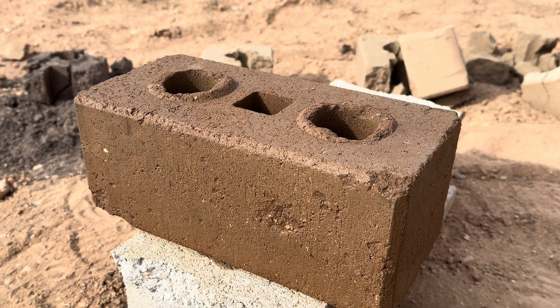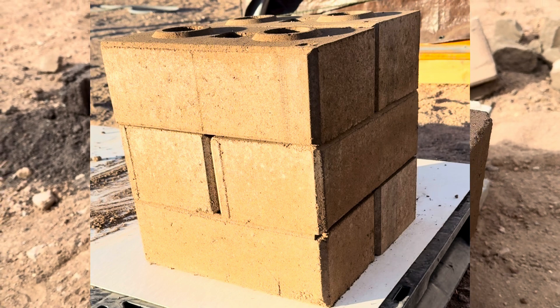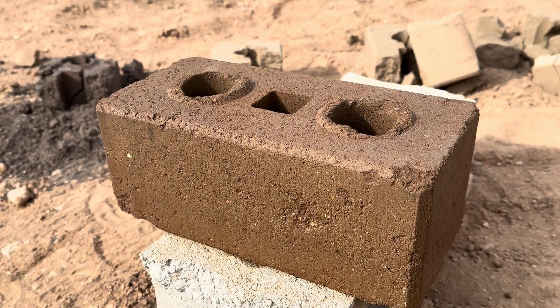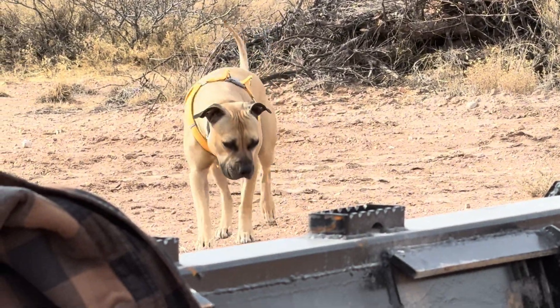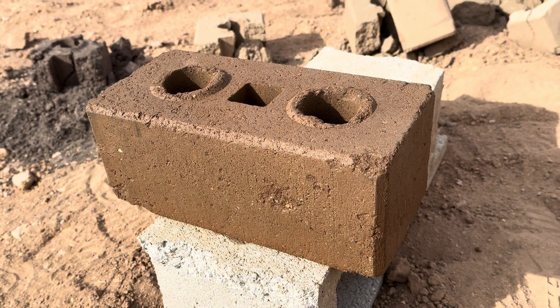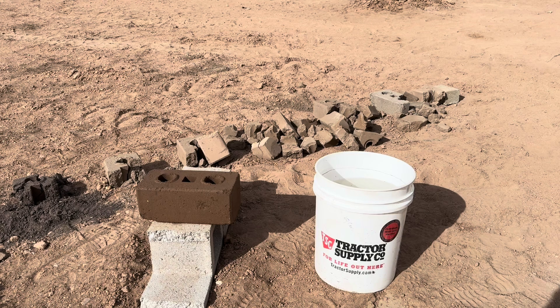If you like that look, just do it with the stick. But once we stacked those things the other day, it looked pretty damn good too — it looks cool. And if you keep it bare like this, it's supposedly breathable, so it's supposedly good for you. Chico is doing his thing. I think this was a good result — I'm very excited. It was definitely a successful experiment. This block was made with 10% cement and our native soil, about a year ago. It was soaked for 24 hours and it didn't break. So what I'm gonna try to do is leave it in the water for about 7 days — one week — and see what happens. Stay tuned.